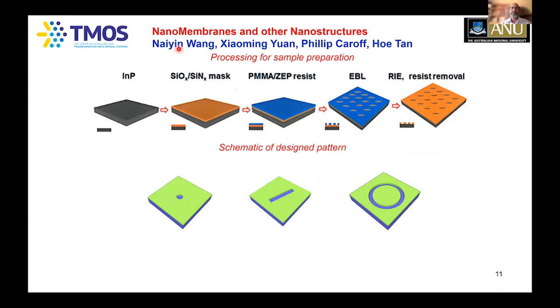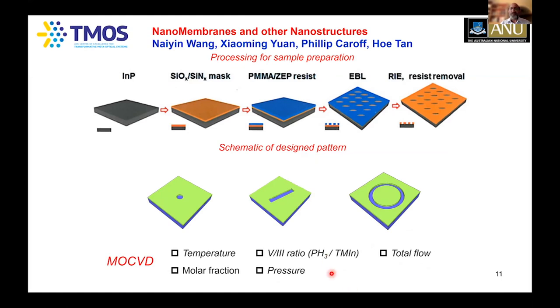During his PhD, he took an indium phosphide substrate, deposited silicon dioxide, put on some photoresist, did electron lithography, and created these patterns of slots and rings, in addition to holes, and then saw what type of structures you can really get. Again, he spent a lot of time optimizing various growth parameters like reactor pressure, temperature, and V/III ratio, and various flows, which I will not have time to go into the details of. I'll just give you the summary of what he's achieved during the 4 years of his PhD.